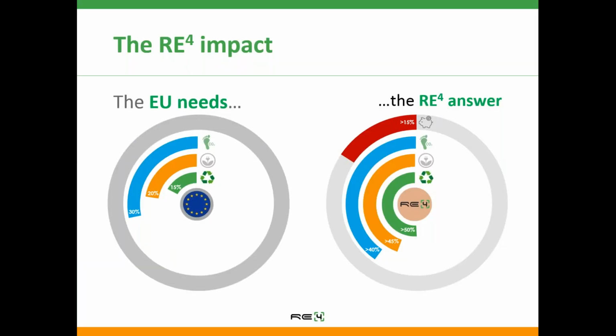In terms of impact, the European Commission set the goal of CO2 saving by 30%, energy saving by 20%, and minimum share of recycled materials in final product of at least 10 to 15%. These are the results that we obtained with the RE4 project. So CO2 saving more than 40%, energy saving more than 45%, and replacement of virgin material with the CDW materials more than 50% on average.